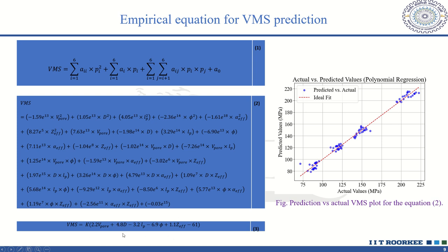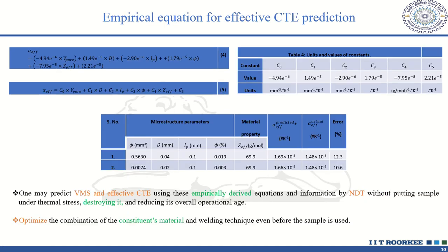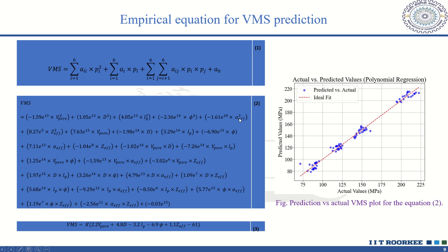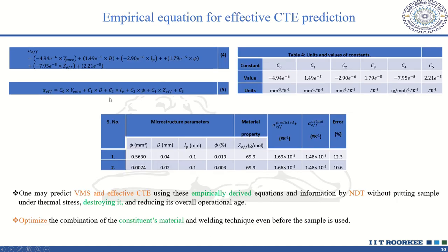And then a linear equation is also derived for VMS by neglecting the higher order degree parameters. And then these two equations, 2 and 3, are equated to derive the equation for the effective CT parameter of the joint. And equation 5 presents the derived empirical linear equation for the effective CT parameter. This equation predicts the effective CT of a brazed ceramic metal joint assembly.